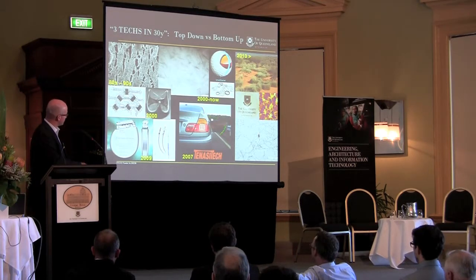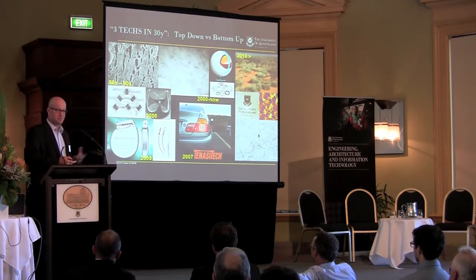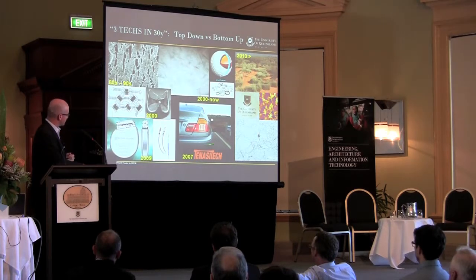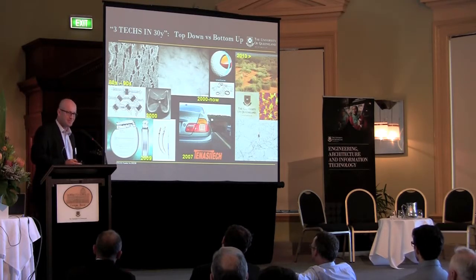But even more recently, we took this platform technology and started putting it into not rubbers, but rigid plexiglass, acrylic, polymethyl methacrylate, and discovered that we could double the scratch resistance using the same family of ceramic fillers. And as it turns out, this is probably looking like our most promising application area, so way, way away from where we started working.